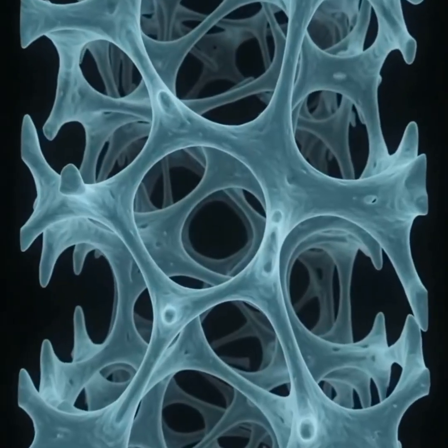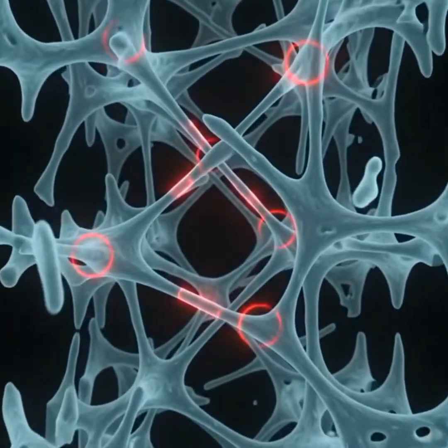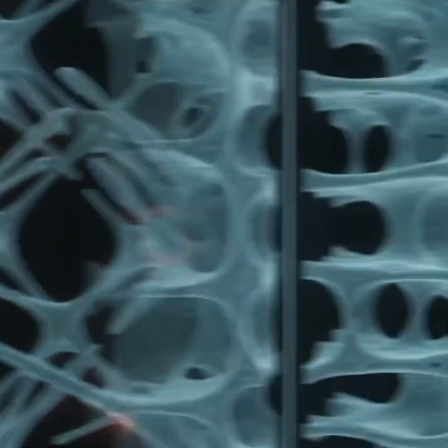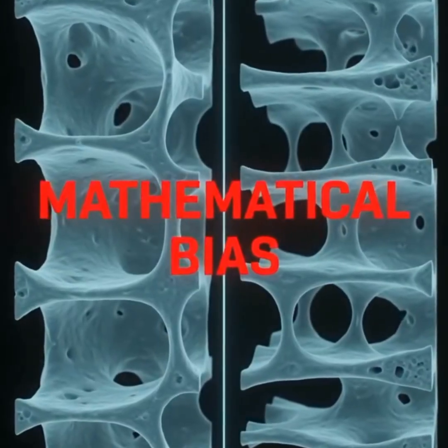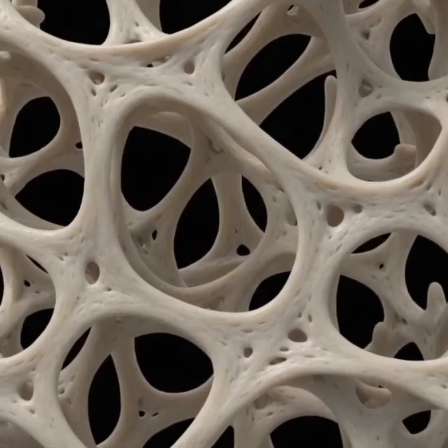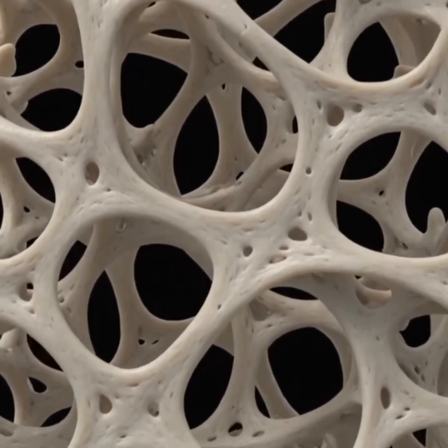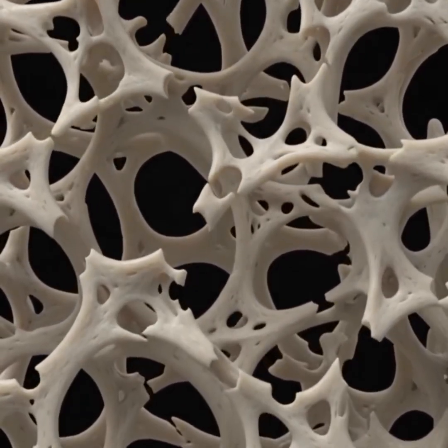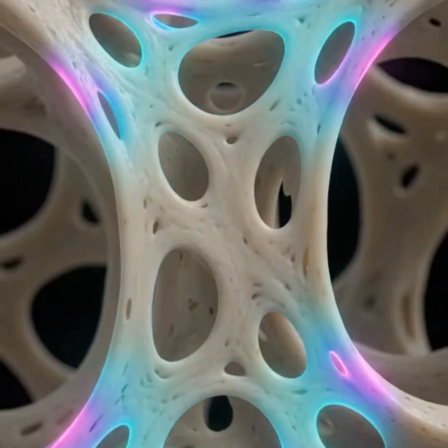This decay was modeled as a plate-to-rod transition. SMI suggested a shift from plates to thin rods. However, modern analyses show that SMI is heavily biased. Decreasing bone volume causes the index to artificially inflate. Osteoporotic bone loss is characterized by physical perforation. This results in a complex mixture of hybrid shapes.